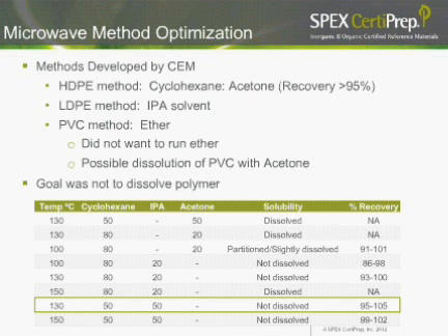So we did a series of experiments at different temperature programs, different solvents, and we found one that gave us a very high recovery rate. It was going to a temperature of about 130 degrees C with a 50-50 mix of IPA and cyclohexane. At this point, we found that the polymer did not dissolve, it did swell slightly, and it gave us a very good recovery of 95 to 105%.